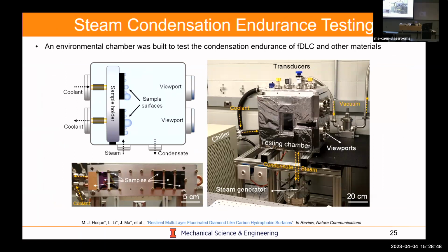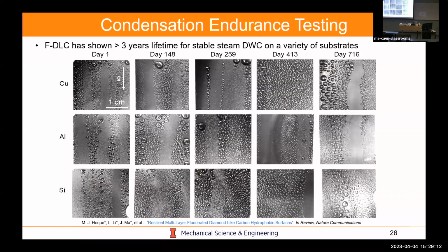And so this is a separate chamber that we developed where we could actually do long-term testing. We could actually mount multiple samples on cold plates and then put it in here. And this work actually started back in 2016. So this is a long time experiment, something which maybe for PhD students, but maybe less so for master's students. And we compare samples to just uncoated HTMS, polymeric, iCVD. And so if we look, this is for copper, aluminum, silicon, day 1 to day 716. So this is actually 2 years.